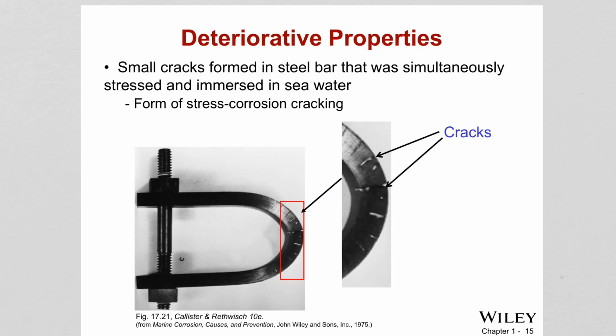So the deteriorative properties, what are these? These are related to chemical reactivity of materials, such as corrosion. And corrosion, you can think about it like the environment is eating up your material, and you are losing material to the environment, and therefore cracks can form. In this case, we are seeing a steel bar which was immersed in seawater, and of course it is under stress, right? And then this combination of the environment and the stress causes cracks to form.